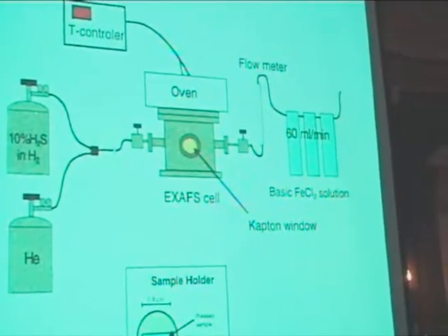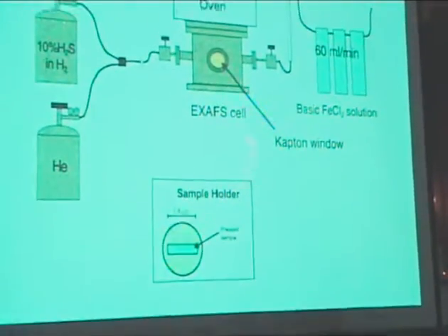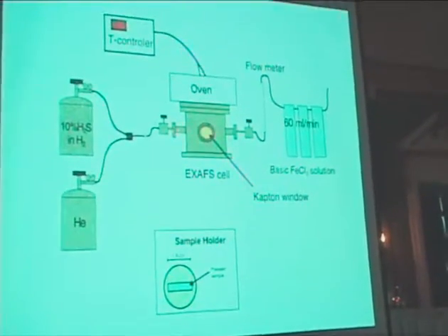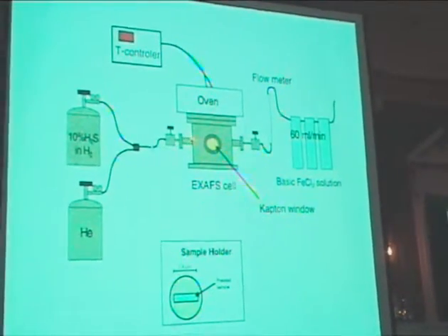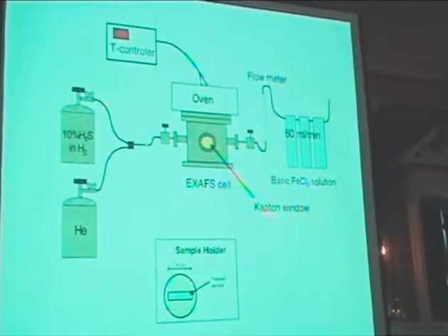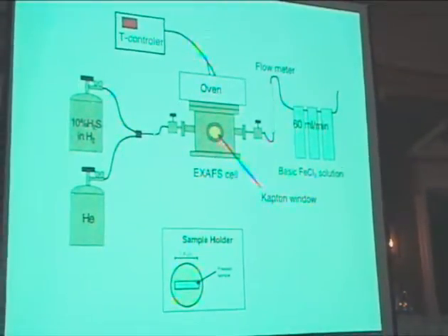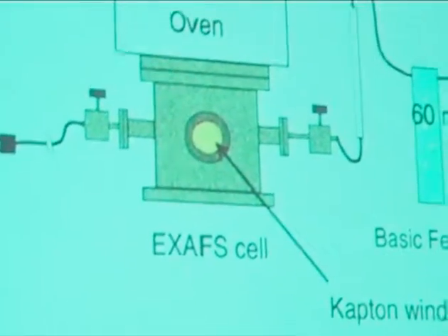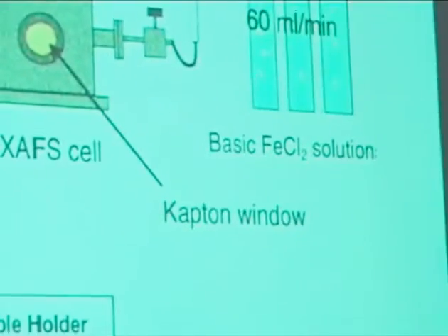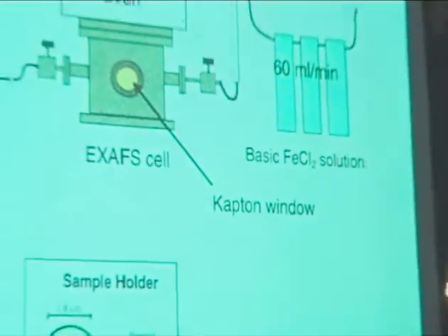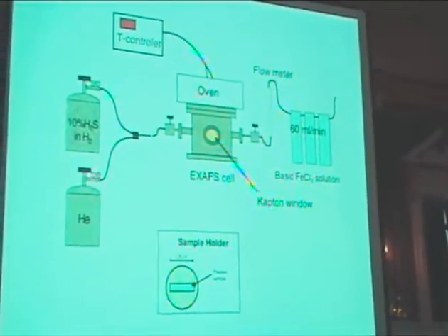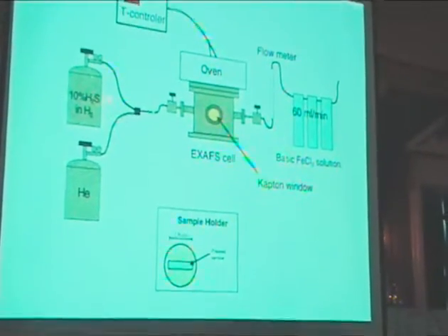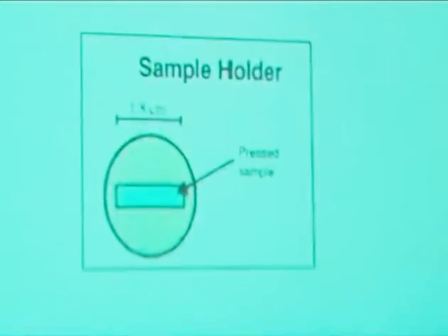You just increase the temperature, and in this case we have our cell, which is a stainless steel cell with Mylar windows, or Kapton windows in this case, and we flow the catalyst precursor, the oxidic form, the heptamolybdate on alumina, and we flow it with hydrogen and 10% H2S in H2.